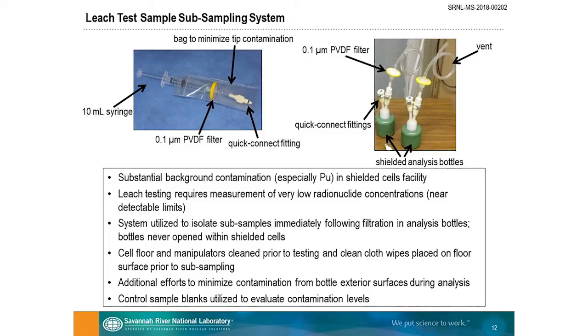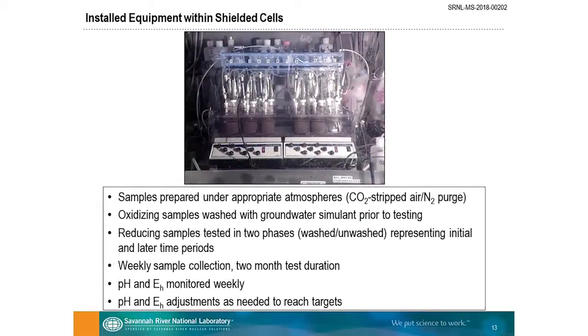Isolated the samples immediately after filtration, so we never opened the bottles in the cells. We cleaned the cell floor. We cleaned the outsides of the bottles once they went to analytical, and were careful not to contaminate it once we got it there. And we analyzed control samples to convince ourselves that contamination was not an issue. And for the most part, almost exclusively, contamination was eliminated. So that's the equipment in the cells with actual samples inside the test vessels.